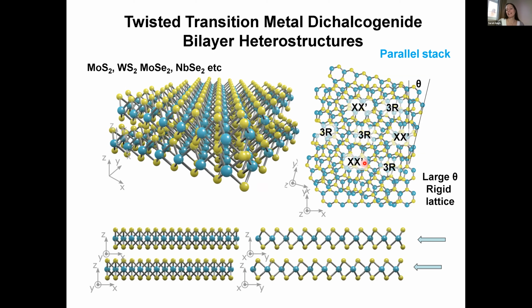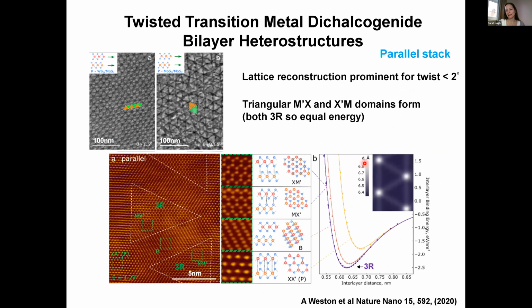So we've then taken these systems looking at various different metals, so tungsten and molybdenum. And you can see that they do indeed reconstruct. So the previous images I showed you on graphene were using the transmission electron microscope. These images are taken in the scanning transmission electron microscope, where we just tune the angles such that we're picking up all of this diffraction information so we can see the domains and the dislocations that are separating these domains.